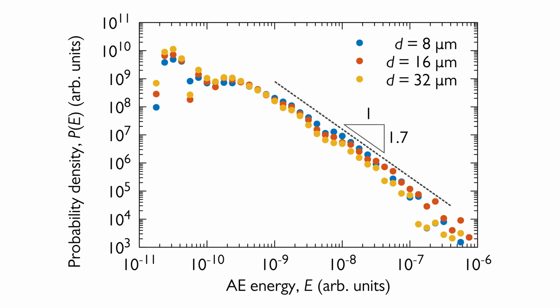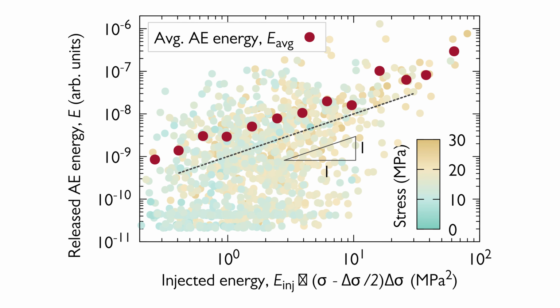The results suggest that there is a physical relationship between the particular stress drops and the corresponding acoustic emission energies. On the following plot, the proportionality of the emitted acoustic emission energy and the plastic strain induced by the local deformation event is clearly demonstrated.